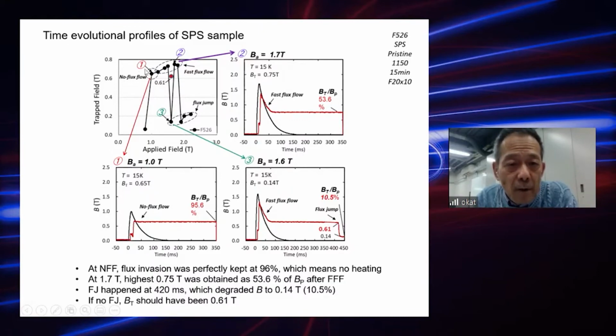So then we may see the time evolution profiles like this on SPS sample. So the red one is number 1 shot, and the number 2 purple line shows the number 2 shot. And then the third one is green, like the shot. At NFF, no flux flow region, flux invasion was perfectly kept at nearly 100%, 96%, which means no heating exists in these areas. So it is ideal.